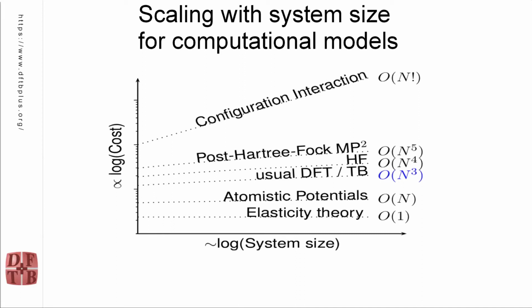There are, of course, some situations where you can drop that scaling behavior, and there is an entire community around what are called linear scaling methods in this family of techniques, where you can drop things down to a linear with system size cost, usually at the expense of a much larger prefactor, so the intercept on the axis for the graph moves upwards. Quite often many of these techniques are also not universally applicable to general systems. They have some requirements on perhaps short-sightedness of the electronic states, which in many cases translates into, for example, insulating behavior or strongly disordered behavior.